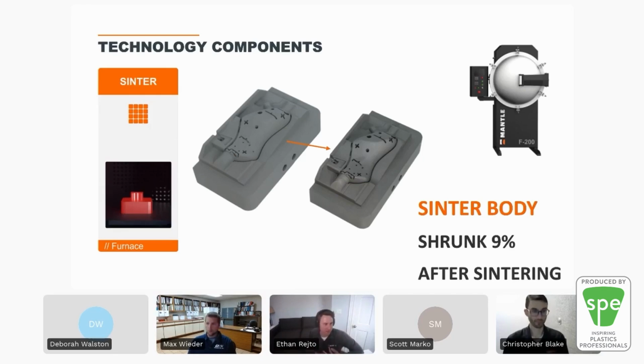What's a little unique about Mantle is that since we've dried and compacted essentially every single layer, our shrink rate's only about 9%, versus a MIM process or other sintering processes are normally closer to 20%, which allows us to control the tolerances much more accurately than these other processes to get you closer to those final tooling tolerances. And of course, with that excellent surface finish, thanks to the machining step.